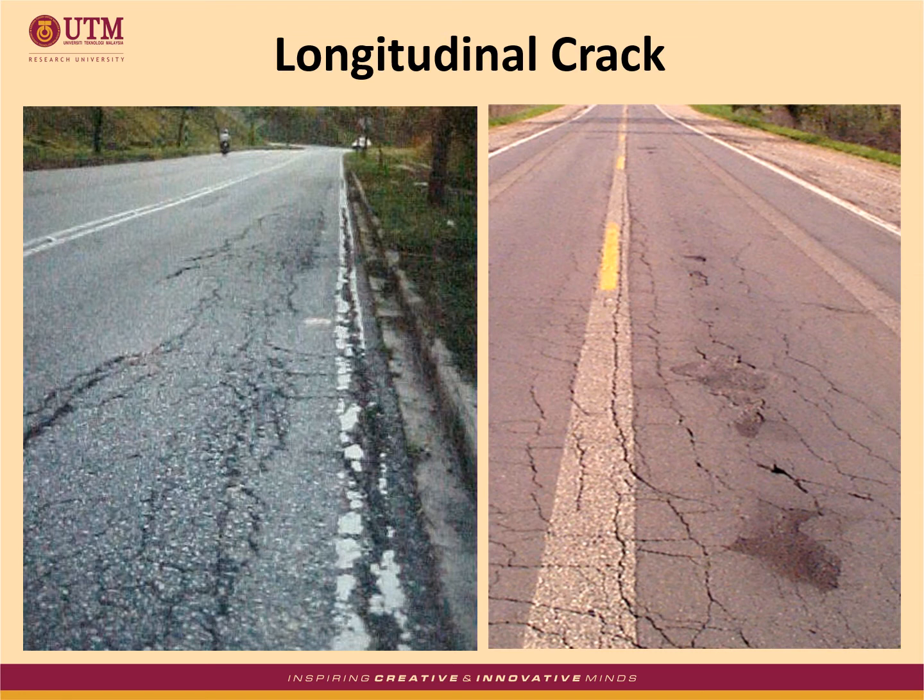This slide shows the photos of longitudinal cracks. Longitudinal cracks are cracks that are parallel to the pavement centerline, and this can be a result of pavement fatigue or poor joints during construction. For treatment, less severe cracks with less than 12 millimeter opening can be sealed to prevent moisture from entering into the subgrade. More severe cracks should be fixed by removing the cracked pavement layer and replacing it with an overlay.